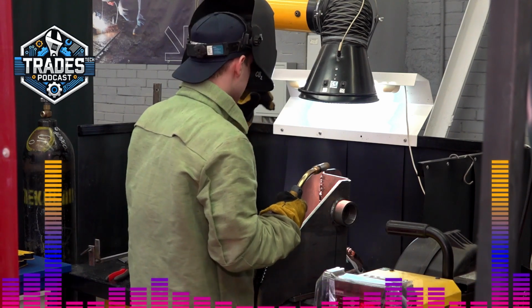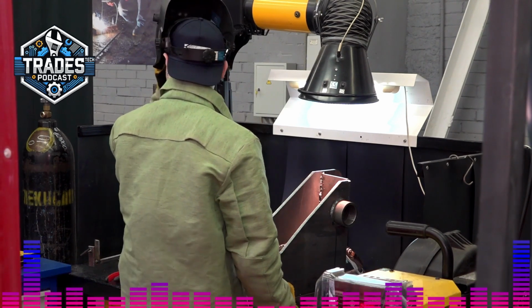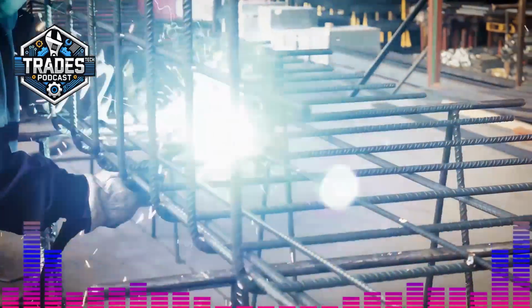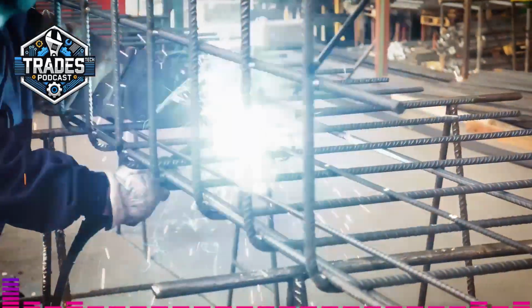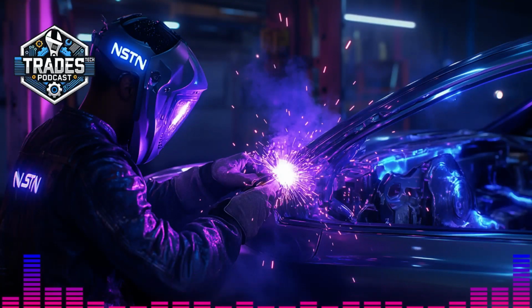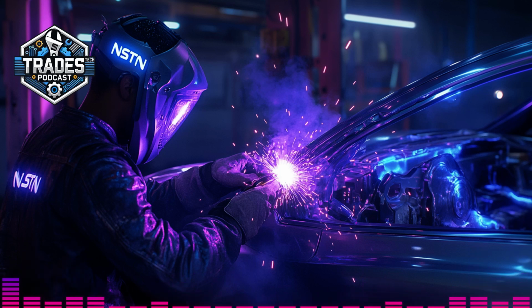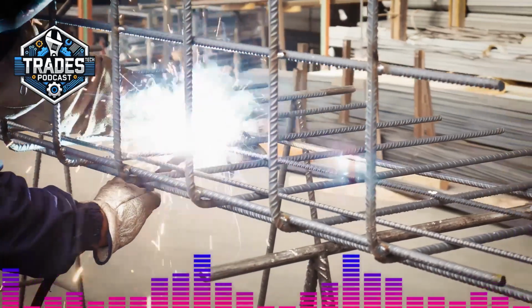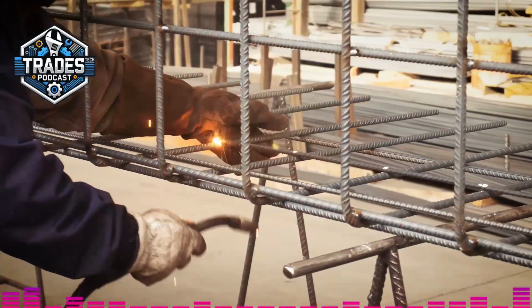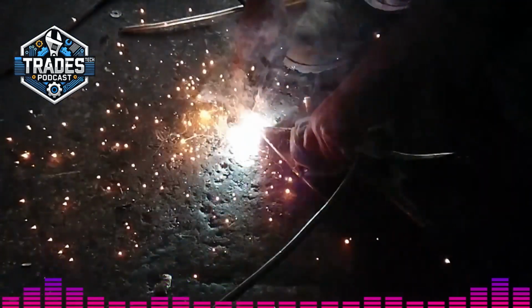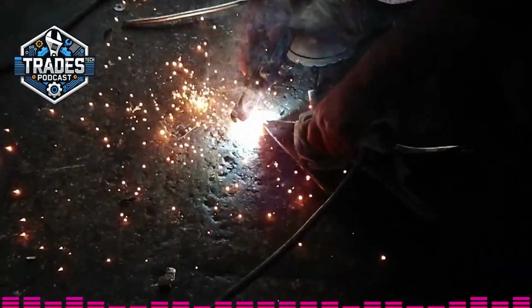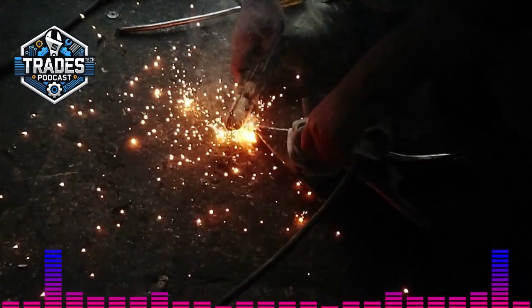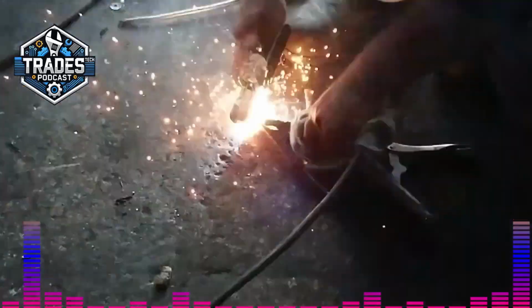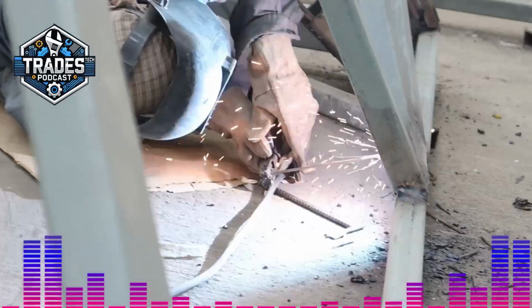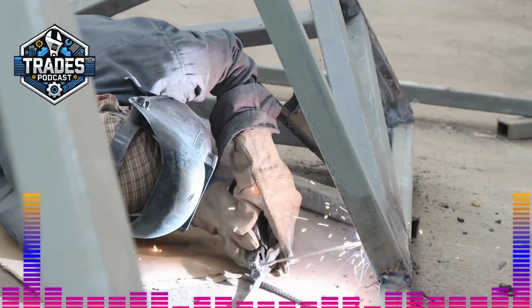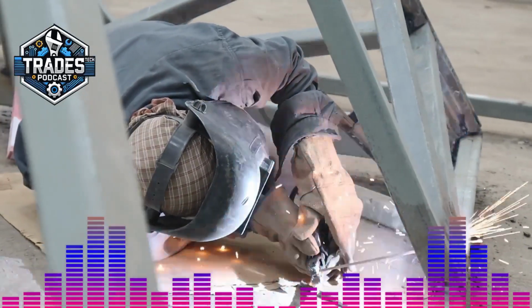It absolutely does. And the flux-core also helps to clean the base metal as you weld. It can handle moderate amounts of rust, mill scale, paint, or dirt that would cause major problems with MIG welding, which requires a much cleaner surface. Again, best practice is always to clean your joint, but FCAW is more forgiving when conditions aren't perfect. Which, let's be honest, is often the case on real-world job sites.